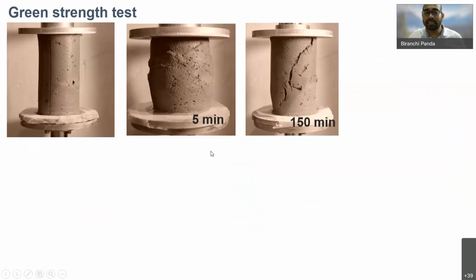So apart from this test, we also developed some new tests where you can see the green strength, because you are loading the fresh material layer by layer. So it is very important to know how many layers you can deposit. If you see this material that is being deposited, it is experiencing a compressive force from the top layers. So we conducted the green strength test to measure the load bearing capacity of this material. At different time intervals, we conducted the test.